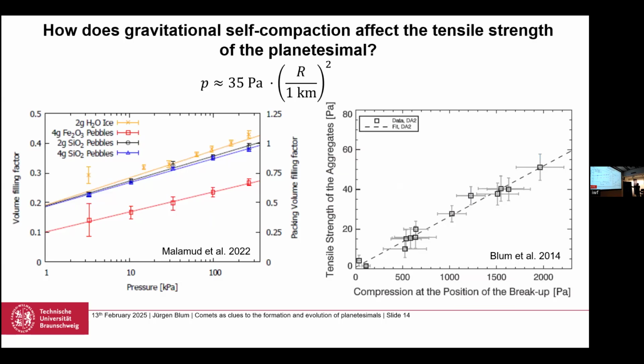Okay, another thing is, so this is the same plot here on the left-hand side as before. Here we also applied compression, but you're seeing this is only a kilopascal, or 2 kilopascals here. So we're considering radii of only a few kilometers, 5-6 kilometers or so in this range. And we measured the tensile strength. So how good is the cohesion among the pebbles? For no stress, 0, the cohesion is on the order of 1 pascal, which is really nothing. That is an important property for comets, as we will see later.